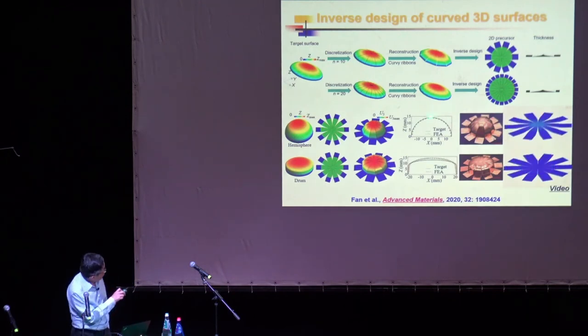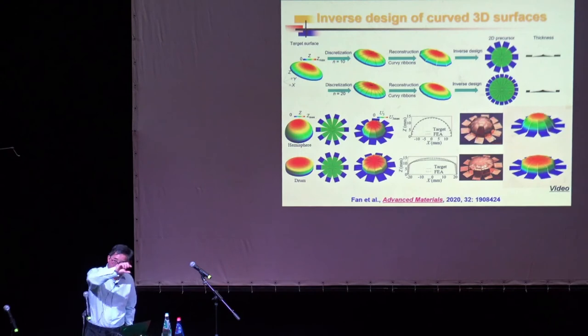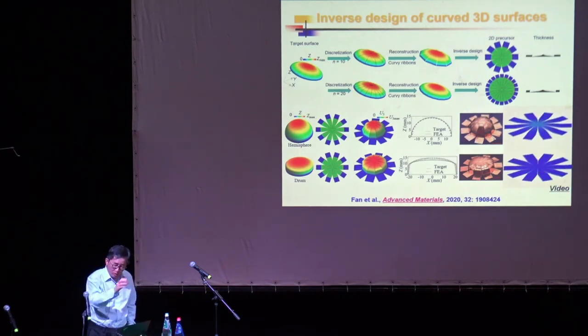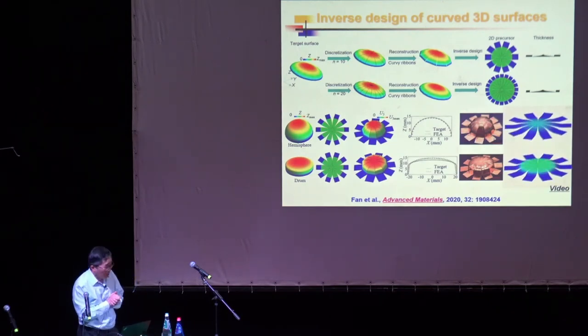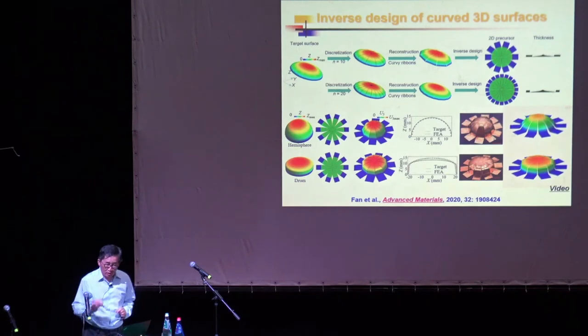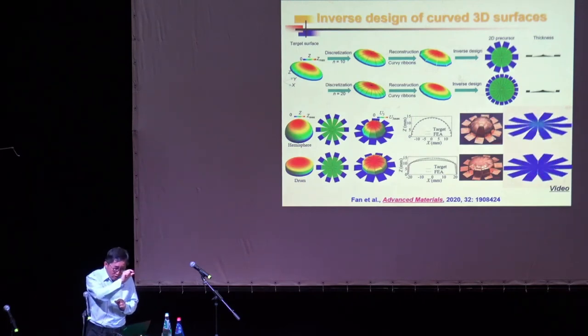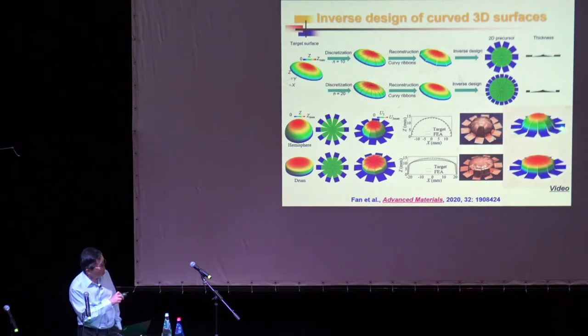For a 3D ribbon, we have analytical theory. We can predict analytically, if you have a 3D ribbon, how to design the two-dimensional 2D ribbon and pop it up into 3D. In this two-dimensional design, what do we change? The width cannot be changed because it has to fit the 3D. It cannot have any gap, but you can change the thickness. It's not uniform. By changing the thickness, you can design the two-dimensional pattern to pop up into 3D.